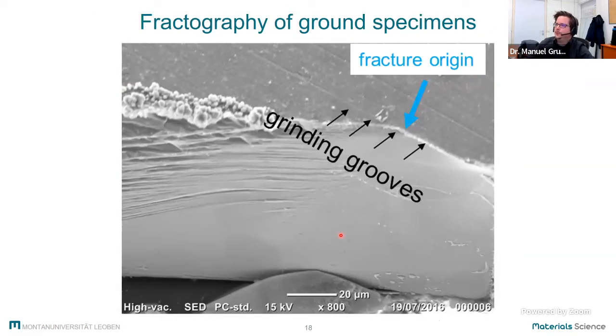If we do fractography on real surface acoustic wave devices, we could see that these grinding grooves are often the fracture origin. So the fracture starts at this flaw on the surface, follows a low energy cleavage plane, and then turns, depending on the stress state in the device, into different directions.